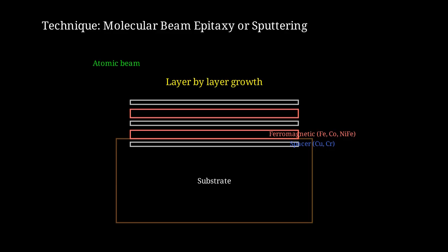Red layers are ferromagnetic materials like iron, cobalt, or permalloy. Blue layers are non-magnetic spacers, like copper or chromium, typically 1 to 3 nanometers thick. The critical parameters are layer thickness, which must be controlled to within a few angstroms, and interface roughness, which must be minimized. Even one monolayer of roughness can reduce the GMR effect significantly.